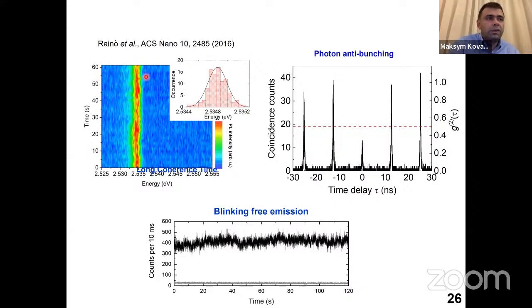Okay, so here you see the emission spectrum from a single quantum dot as a function of time. So it's a stable single photon emission. There is clear single photon emission confirmed by the anti-bunching experiment, and these quantum dots do not blink much. Just to put it in perspective, before the perovskite quantum dots, all the other kinds of the colloidal quantum dots have been unstable. They blinked a lot, and at such large sizes, they had not been single photon emitters.